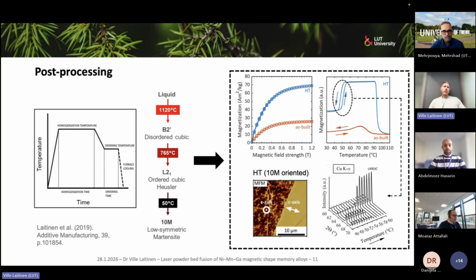And then we have the secondary treatment, which is the ordering temperature. This is just above the transition temperature from the B2 disordered cubic phase to the ordered L21 austenite. The point of this treatment is that we are setting our atoms in the exact right positions just before we cool over this transition. Out of these two treatments, this is the more important one for the magnetic properties. If we go over this transition too fast, we lose some of our long-range order, and then we will have inferior magnetic performance.